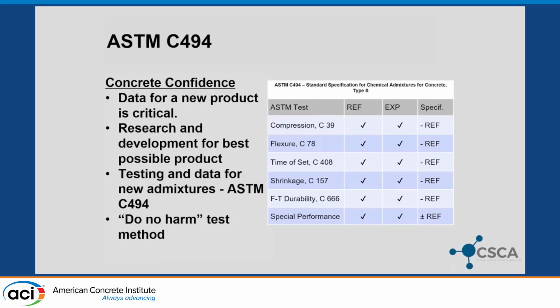So what the C494 gives the industry, I wrote it up there as a do no harm test. And I don't mind the argument on that, but what you'll see from using the C494 is it lets the engineers, the designers, the specifiers know what your product is going to do that's harmful to the concrete. Oftentimes people are kind of confused when you look at it. You're doing a comparison between a reference concrete and that same concrete with your technology. And it's a fresh and hardened properties comparison. And you can have a 10% reduction in strength and still meet the ASTM, or I still pass the ASTM C494 Type S. And the reason is there are some admixtures out there, like for microbial induced corrosion, where getting strength back is nothing.